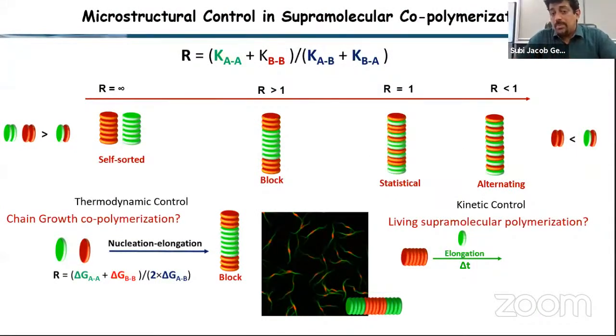And that is understood based on the reactivity ratios of the two monomers, right? If the reactivity ratio is infinity, or otherwise AA interactions and BB interactions are stronger than AB interactions, you always get self-sorted structures. And if the AB interactions are stronger than AA, you will get alternating structures. And something in between, where the reactivity ratio is close to 1 or slightly greater than 1, you can get block systems or statistical systems. We know that in conventional polymers, the reactivity ratio is determined by the reactivity of the functional groups, right?